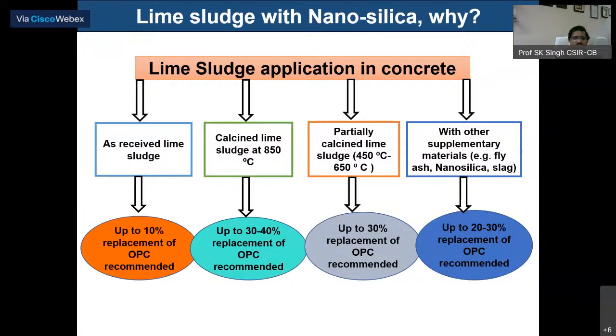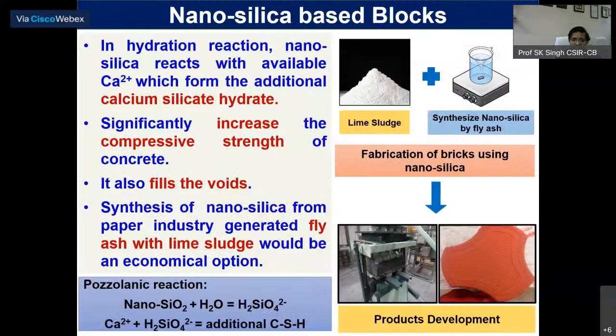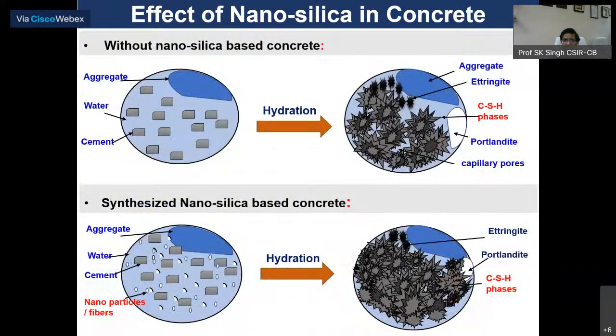And we can use calcined lime sludge in different ways, in concrete. So this is our way, and we have done it this way. Here, if you look, when we convert it into nanosilica and add it, more calcium silicate hydrate phase is being generated than when we are not adding it. So we can have benefits from this in making a high-strength or better durable product with the lime sludge.